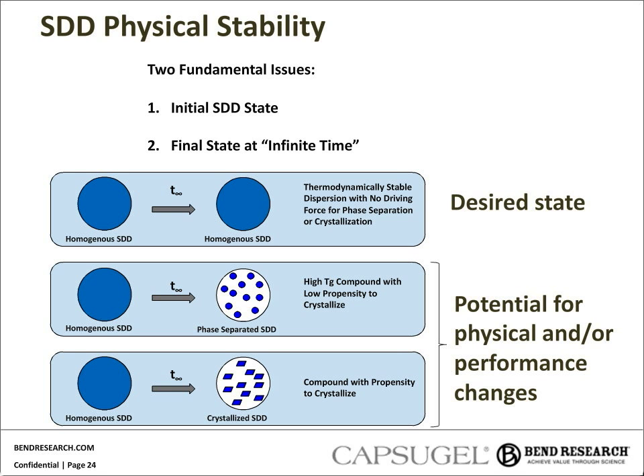In the first case, the top case, we're looking at a solid solution. Effectively, the drug is dissolved into the polymer. It's a thermodynamic system, and if you let that material sit over an infinite amount of time, it will never come out of that solid solution. It will always be homogeneous. The limitation is that oftentimes drugs don't have very high solubility in the polymers, and therefore you are limited in your loading. Another challenge with that type of formulation is that thermodynamics applies at a given temperature and given condition. That phase diagram is going to change as you change temperature or storage condition, so it can oftentimes be challenging to be predictive about physical stability in those cases.